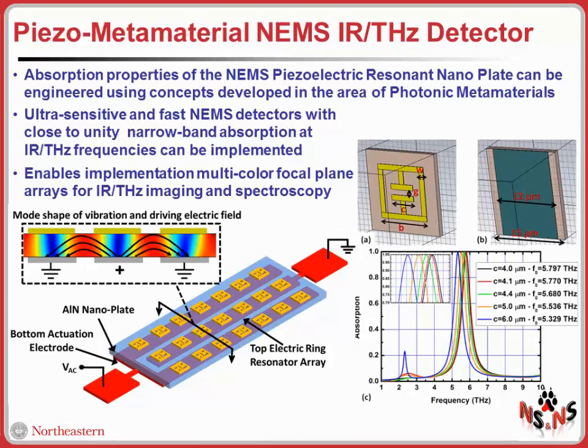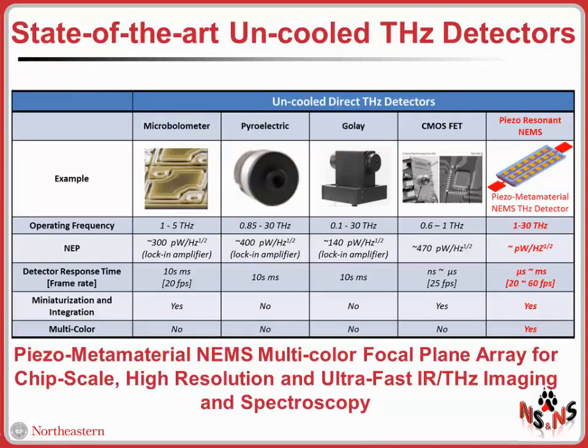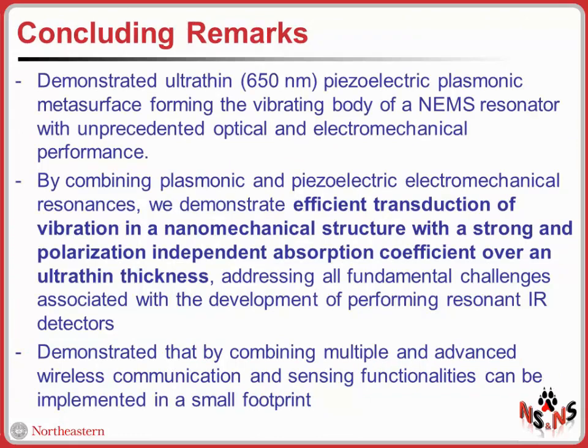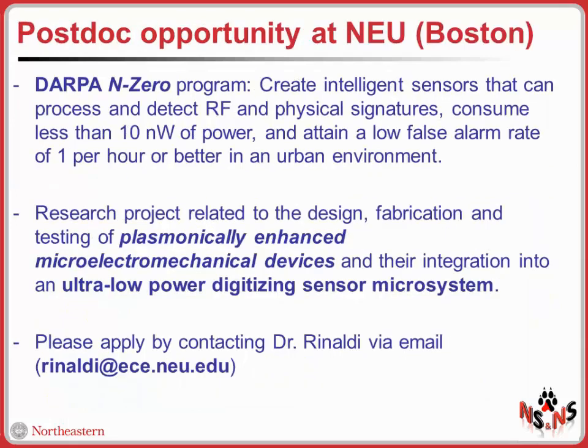For example, using concepts that have been very well developed in the photonic metamaterial community, such as electric ring resonators and things like that. And that, of course, has really high potential in the terahertz, in the 1 to 30 terahertz range, where there is a large need for uncooled thermal detectors that are miniaturized, low power and so forth, and also spectrally selective, opening interesting opportunities for multispectral imaging and spectroscopy applications. So in conclusion, what we demonstrated is that it's possible to combine electromechanical and electromagnetic resonance in a single ultra-thin piezoelectric film and use that idea to build plasmonic resonators with quite interesting and unique infrared sensing performance.